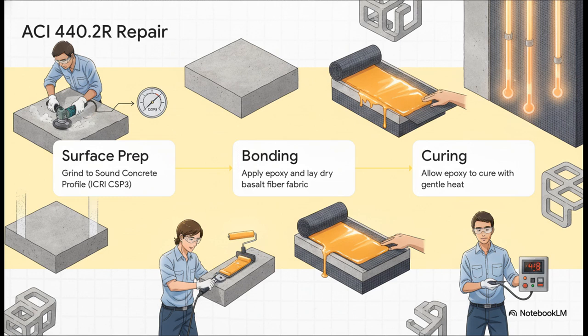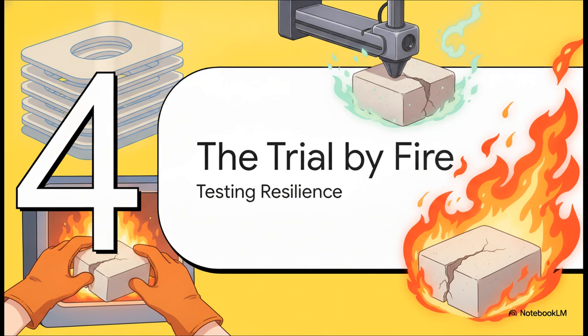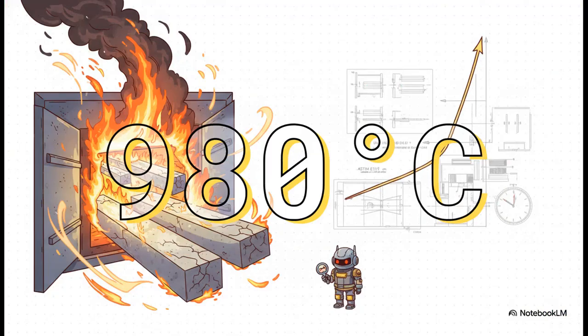The epoxy needs 48 full hours to harden, and they actually use a gentle heat of about 40 to 50 degrees Celsius to accelerate it, which actually improves its performance at high temperatures later on. Okay, so we've printed them, we broke them, and we meticulously healed them. Now for Section 4, the trial by fire. 980 degrees Celsius. That is the number that matters here.